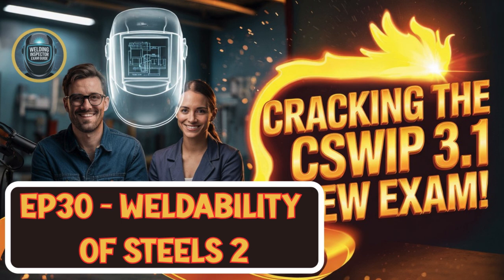Right, for carbon manganese, medium carbon, and many low alloy steels, you might be looking at a CEV between, say, 0.4 and 0.5. With these, if the metal is thin, you might still get away with no preheat. But as it gets thicker, you'll definitely need some preheat, maybe a low level like 50 or 100 degrees C. And using low hydrogen welding consumables and processes becomes much more important here to avoid cracking.